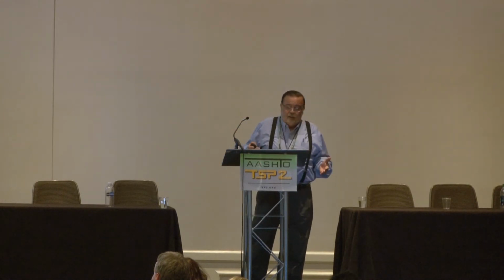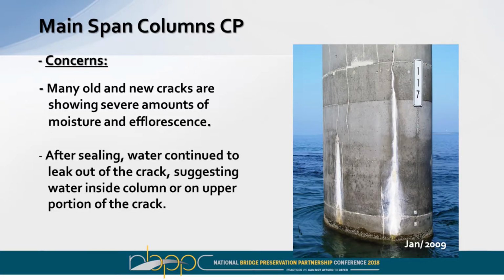We already know that, I know that epoxy coated rebar, for some reason in Florida, has never worked, has never held back corrosion. Now, we know that we have water getting into the rebars, so we try to seal them. Now, for some structural reasons, either movement of the columns or expansion of the concrete, the cracks keep reappearing, or even some of the cracks that have been sealed, the sealing material cracks. So we have water penetrating our concrete all the way to the rebars.